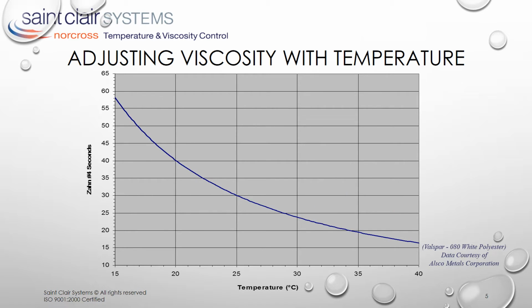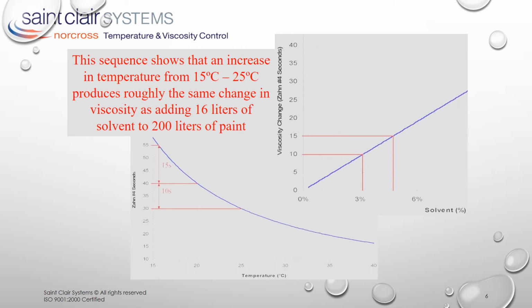Here we can see that the roughly 5 degrees increase in temperature from 15 degrees C to 20 degrees C produces a 15-second reduction in viscosity. Likewise, the next 5 degrees C from 20 to 25 represents an additional 10 seconds reduction in viscosity. So, this sequence shows that the 10 degrees C change in temperature from 15 to 25 degrees C has roughly the same effect as adding 16 liters of solvent to a 200-liter drum, or 4 gallons of solvent to a 50-gallon drum, again, whichever way you want to look at it.